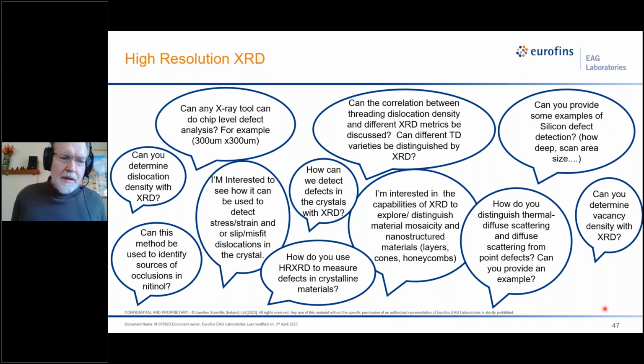Okay, so there are a lot of questions that came in about the crystal quality or how you measure defects. The first thing we have to do is talk about the difference between high resolution XRD and normal XRD. A normal XRD source is polychromatic, so even though you're looking at copper K alpha, you're getting a continuum of X-rays as well as K beta coming out of the tube, and it's divergent. For high resolution diffraction, you need to get to where you have only a single wavelength, in this case copper K alpha 1, and it's a parallel beam. So you go through some kind of monochromator to do that.